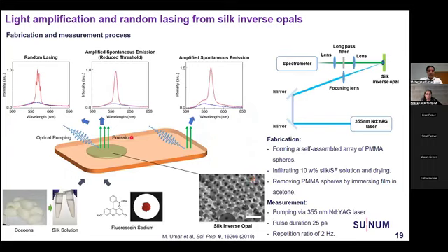In this case, we take the silk biopolymer, because silk biopolymer is fully biocompatible, and we use a dye that is also biocompatible. Sodium fluorescein dye is also biocompatible, and a mixture of silk and sodium fluorescein will be a fully biocompatible device. We make the silk inverse opal by using nanospheres of PMMA. First we make the PMMA spheres on a silicon substrate, so they are uniformly assembled, and then we dropcast the solution of silk and sodium fluorescein onto the nanoparticles, and then we etch after drying.